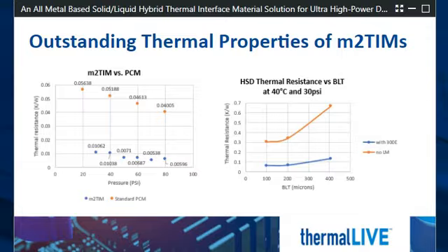This slide will show us outstanding thermal properties of M2 TIMs. On the left side, we can see how thermal resistance will change with the pressure for M2 TIM and one phase change material. Thermal properties of M2 TIM are much better compared to phase change material. We can also see that for M2 TIMs, the thermal resistance doesn't change too much with the pressure. That means that we can have low thermal resistance even with a very low pressure. Just like with liquid metals, thermal resistance of M2 TIMs doesn't change dramatically with thickness. Basically, this combination of solid and liquid metals will have the best properties of each type, solid and liquid metals.